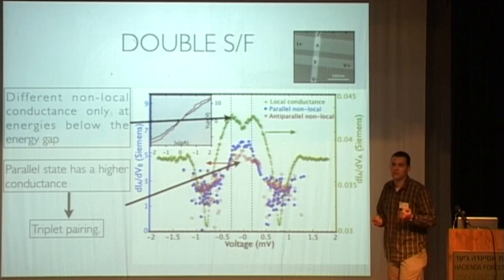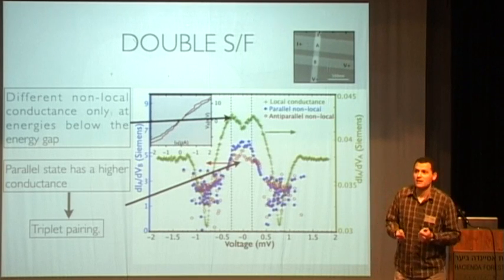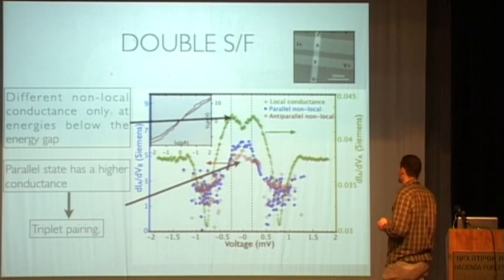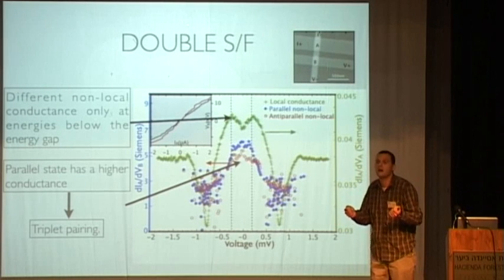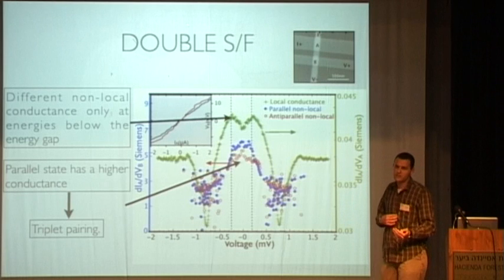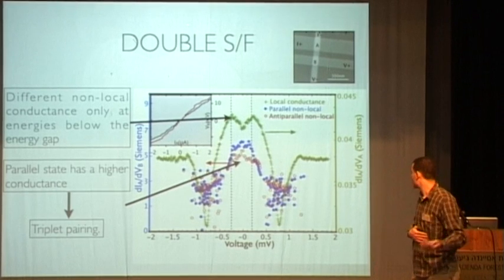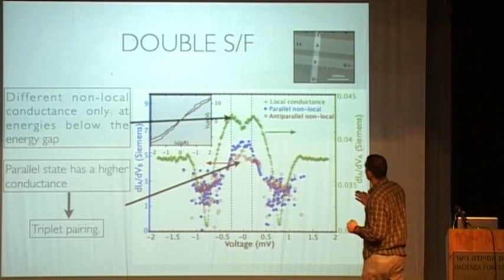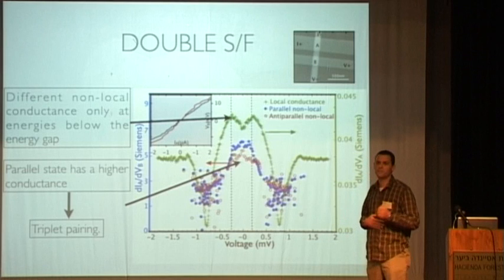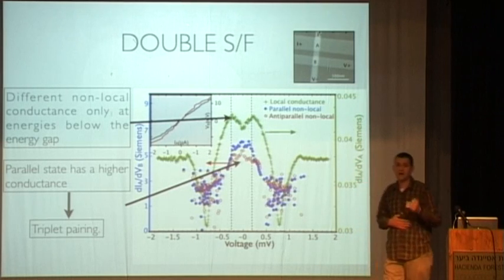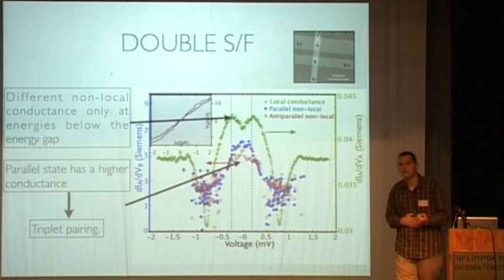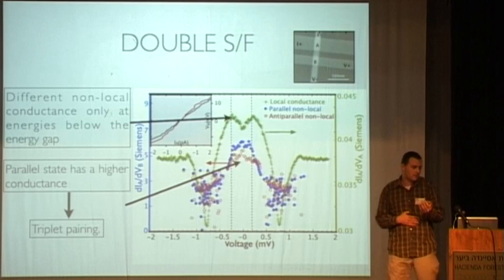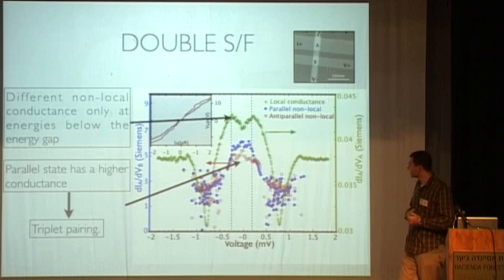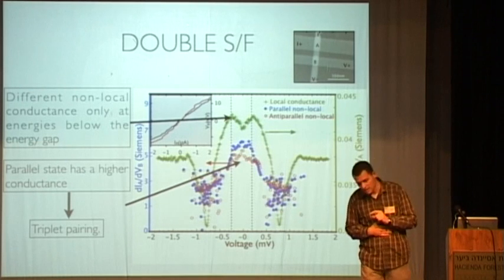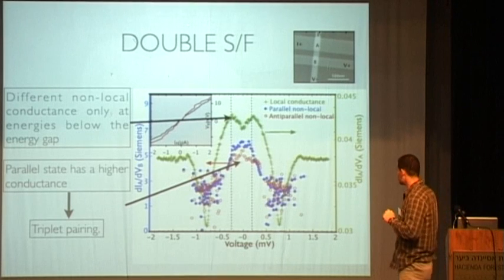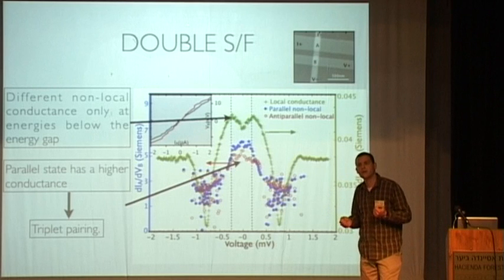interesting stuff happens. And why is that? Because these peaks are roughly the energy gap, or the strength of the interaction between the electrons. And once you go to higher energies, you break the pairs. So nothing interesting happens at higher energies. Now at low energies, in the middle, you see a distinct difference between the parallel configuration and the anti-parallel configuration. And you see that the parallel state has a higher conductance. So the cross-Andreev is more effective. And basically what it means is that we have a triplet pairing. In a singlet system, this non-local conductance will be opposite. Now, I forgot to mention, but what I'm showing here is the voltage.